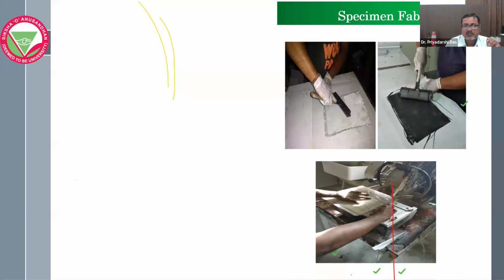And this is the diamond cutter, where after curing the plate, the beams have been extracted through this diamond cutter, which, through continuous pouring of water, will get the desired shape of the beam. Here, the beam size is 25 mm width, 250 mm length, and the thickness has been measured through the slide calipers. Here it is 2.6 mm.